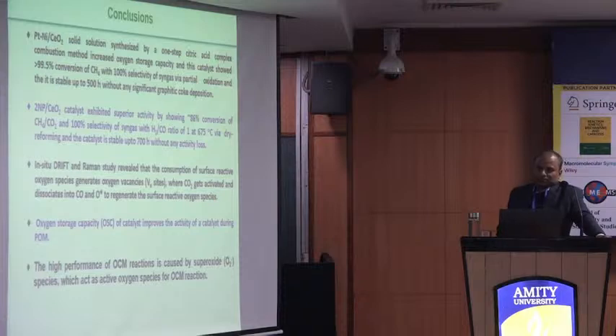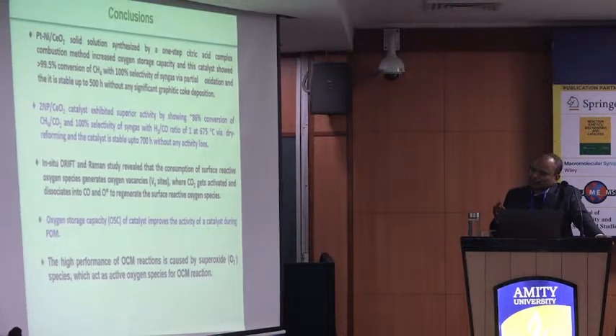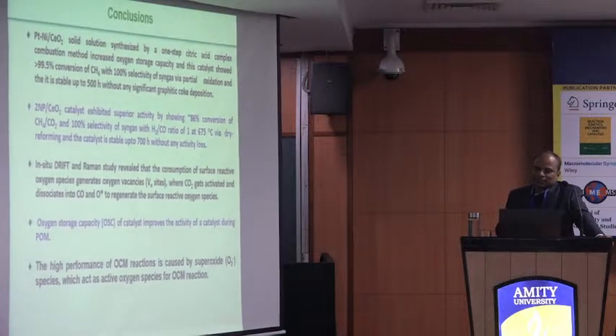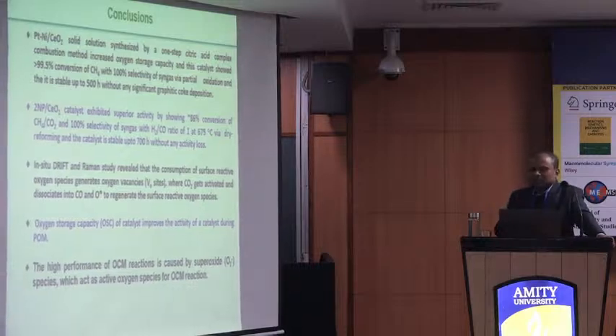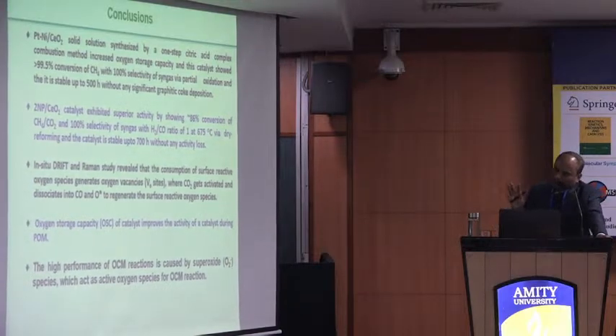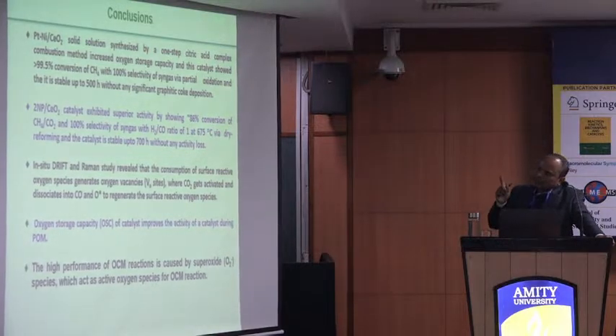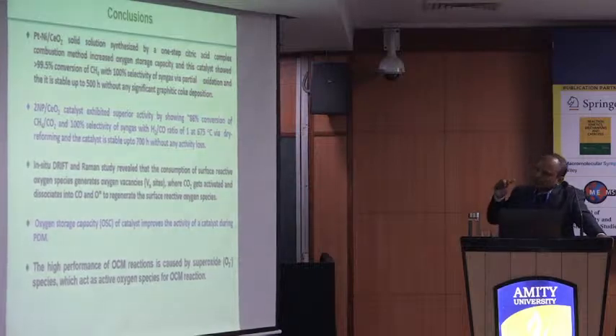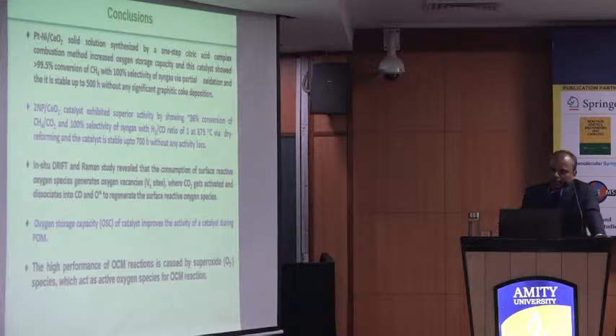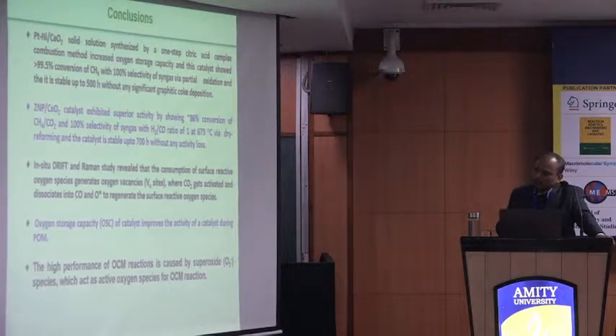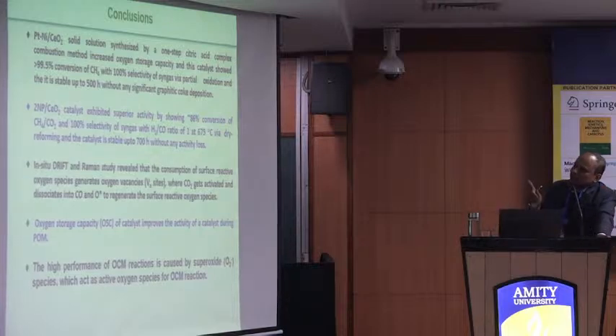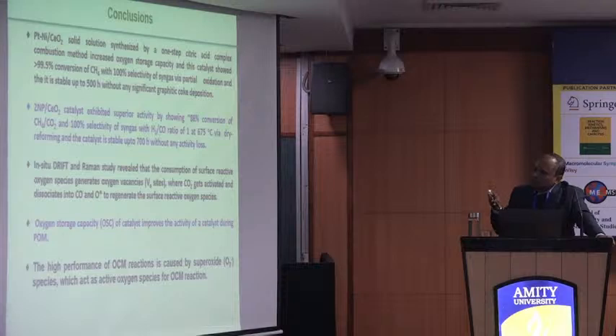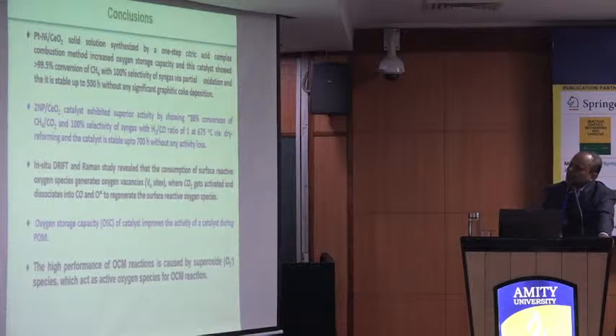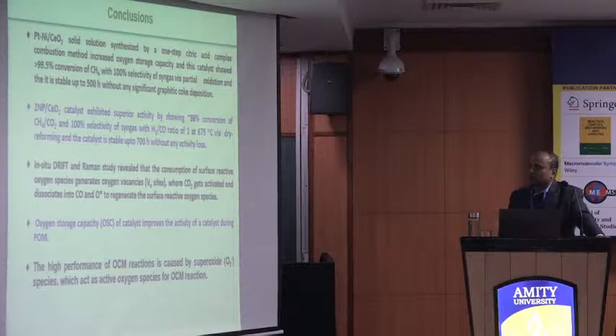And finally, the conclusion: platinum nickel supported on ceria, prepared by the one-step citric acid combustion method, showed almost 100% methane conversion and 100% selectivity for syngas in partial oxidation, and this catalyst is stable for 500 hours without any formation of graphitic coke. For dry reforming, we found that 2% nickel, 0.5% platinum supported on ceria is showing around 86% methane conversion and more than 90% CO2 conversion, and it is showing 100% selectivity for CO at 675 degrees, and this catalyst is stable for 700 hours.